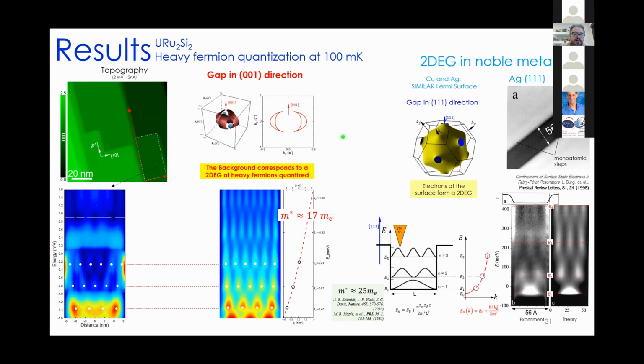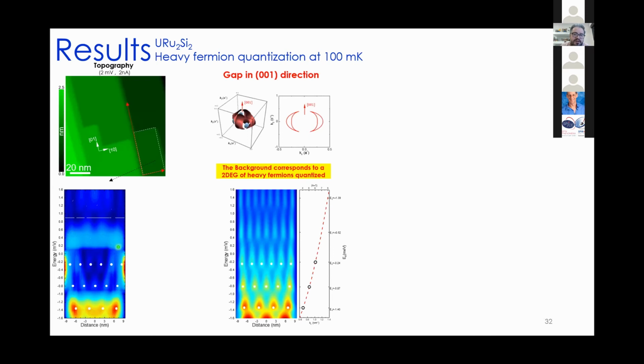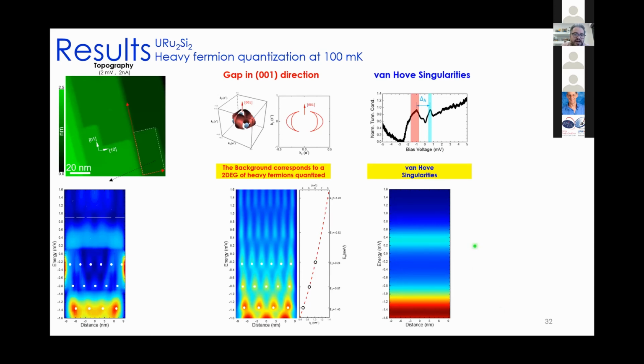Here, we can also see that on top of the background, you observe these two features that enhance the value of the density of the states at energies that are close to 0.4 meV and minus 1.4 meV. These two features, in particular in these positions, are related to the low energy excitations that we have in the uranium-ruthenium-2-silicon-2, and we have also measured that excitation using STM. They are known as Van Hove singularities, and they connect to the hybridization gap, but I'm not going to talk in detail about this. I just want to say that we assume that the behavior of the Van Hove singularities is constant with the distance, and here we simulate them as two Lorentzian functions.